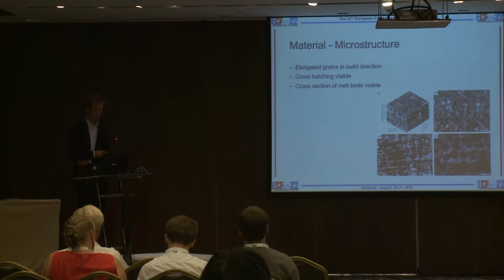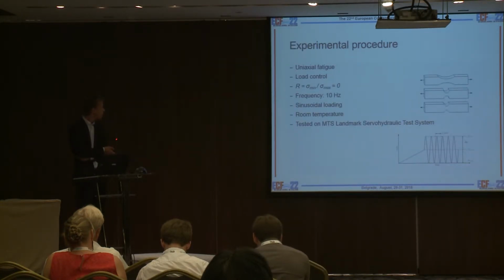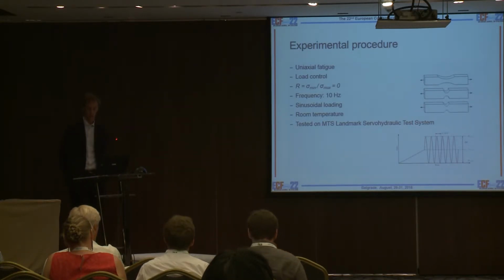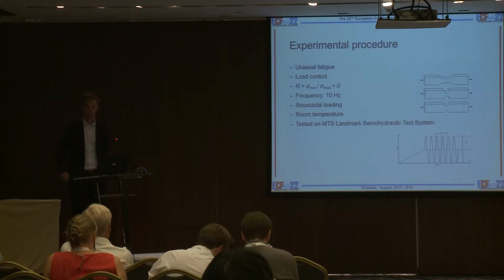We looked at the microstructure of the material. In the top plane, we see the cross-hatching from the building, and we can see elongated grains in the building direction, and also we can see the cross-section of the melt pools. So this is the standard as-built material. We have been performing uniaxial fatigue tests on these specimens by load control with a loading ratio of 0 and a frequency of 10 Hertz. Sinusoidal loading at room temperature, tested on a servo-hydraulic system.